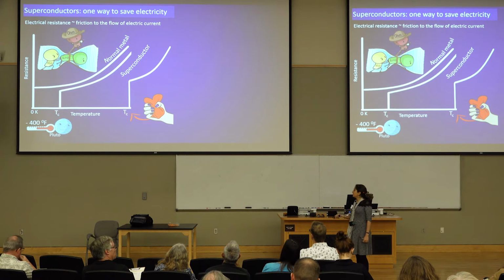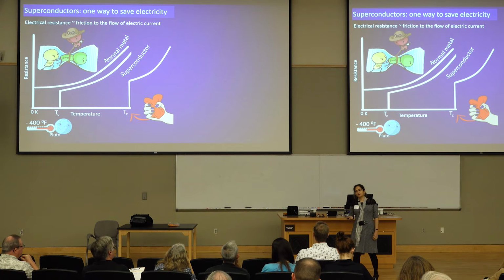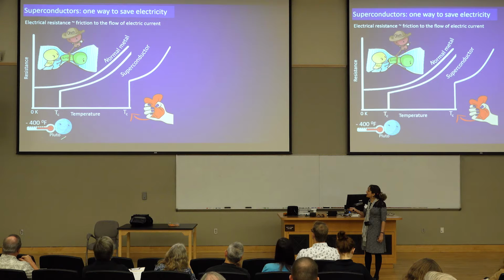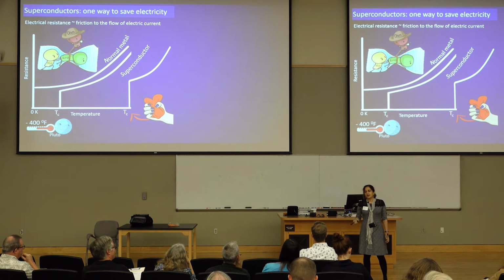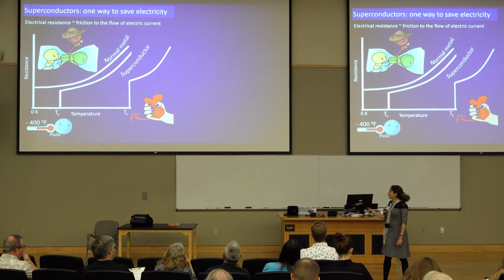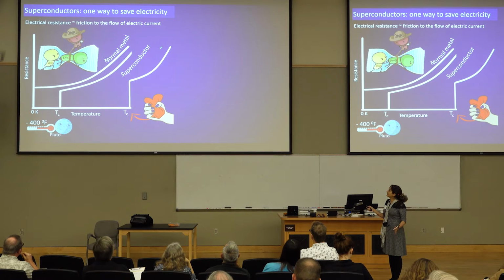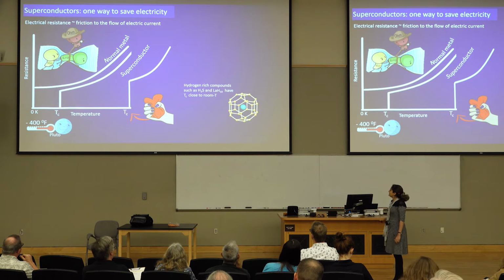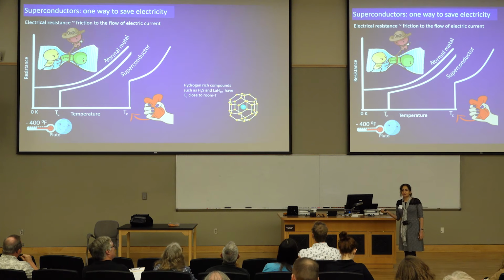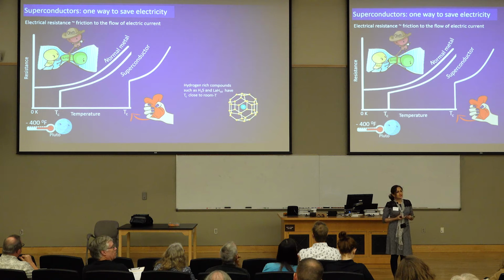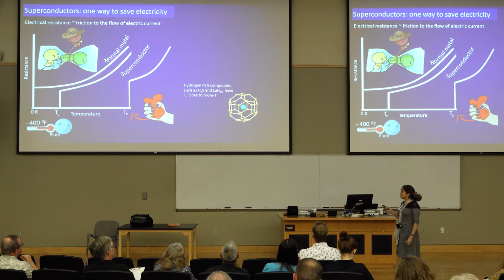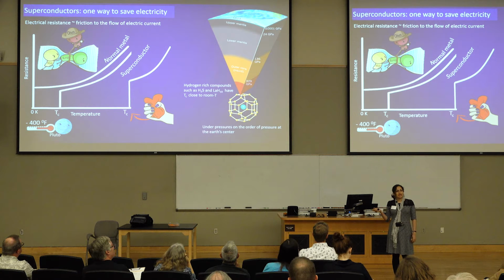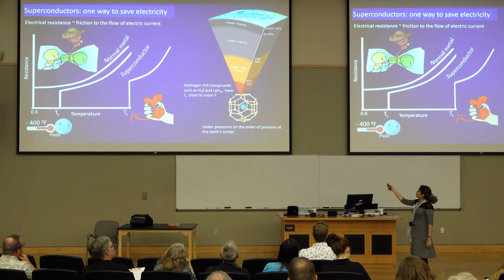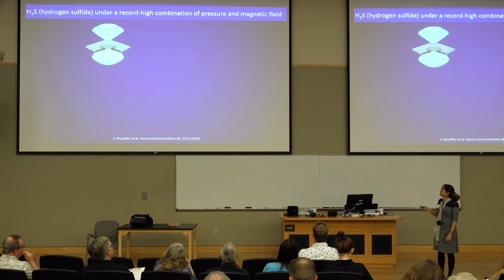But unfortunately, this superconductivity only occurs at very low temperatures. This TC is as cold as the surface of Pluto, and that makes it impractical for routine applications. But there is one way to increase TC, and that is to squeeze the material. In fact, it has been shown that hydrogen-rich compounds, such as hydrogen sulfide or lanthanum hydride, can be superconductors at temperatures much closer to room temperature, and thus they are called high-temperature superconductors. But the price to achieve this high TC is to squeeze the material at hundreds of gigapascal pressure. This is the order of pressure close to the center of the Earth. In the lab, we can achieve this pressure by squeezing the material between the tips of 2 diamonds.